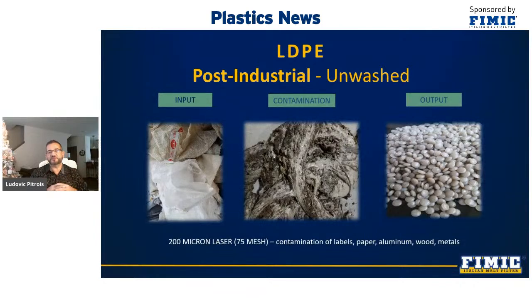Here, we see post-industrial polyethylene with the same screen and contaminants. In addition, we can clearly see paper and adhesive tapes. The final color of the pellet changes according to the type of plastic and its contaminants, but the color is also affected when the temperature and pressure are higher than normal in the filter area. Our filter has the largest filtering area or surface on the market, with only one screen, allowing better temperature and pressure control in the filtering area, avoiding material and odor degradation and color change.